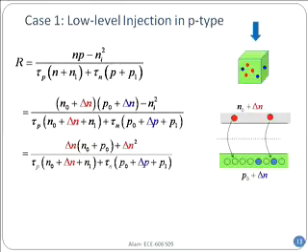Similarly, if this is a p-type material, p-type means it has a lot of acceptors, then it has relatively few electrons, right? And so which term can I get rid of? I can get rid of n naught. Why? Because it's a p-type material, lots of holes, few electrons. And that's why I get rid of the n naught compared to p naught. You see, you'll have to make a relative comparison. And once I have done that, I will simplify in every case.